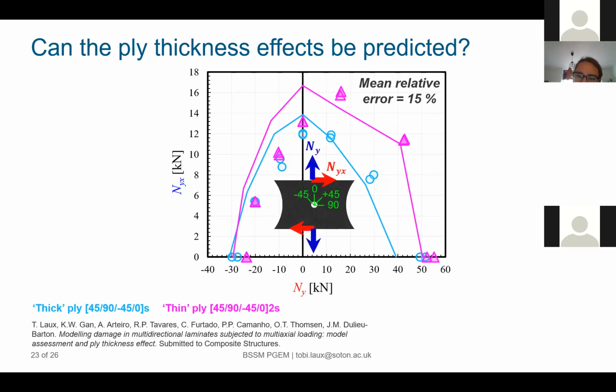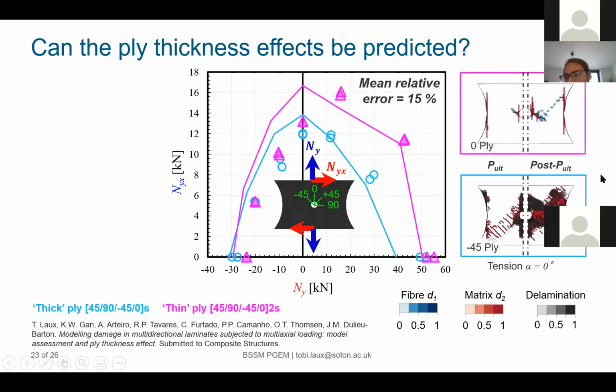But more interestingly, that's a reminder of how the fiber orientations are defined here in the specimen. More importantly, if we look at the internal damage prediction, here for laminate 1, and this is for laminate 2, we actually can see why the strength is so different in the prediction. And the reason for this is because the failure modes are totally different in the model.